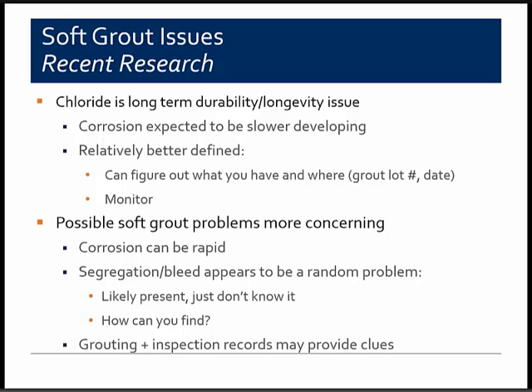And if there were any issues and soft grout has formed and is now present, corrosion problems may manifest very, very rapidly, as has been observed already in Florida and Europe, much more rapidly than would be expected with the chloride issue. And because of the randomness of the soft grout formation, it is at a minimum possible that soft grout regions exist in the tendons of many bridges and structures, and we just don't know it.